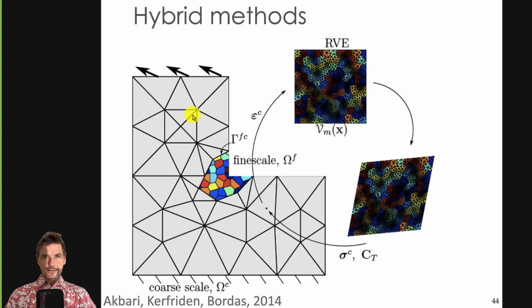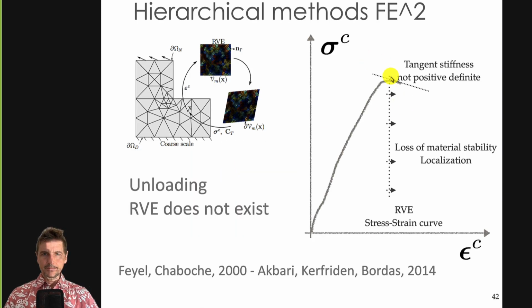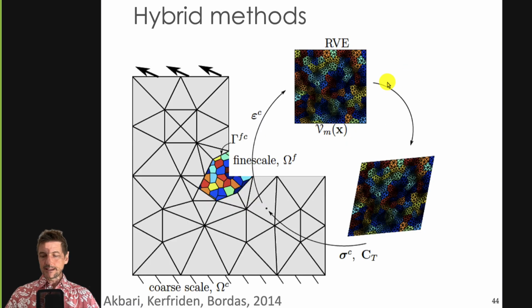Or what you can do is come up with a hybrid method where as soon as you reach material instability, which is the peak here, what you do is extremely simple conceptually but very difficult to implement. You replace the elements where you reach the peak by one representation of the microstructure, one instance, one statistical draw. So you throw some dice and say, okay, here I assume the microstructure looks like that.